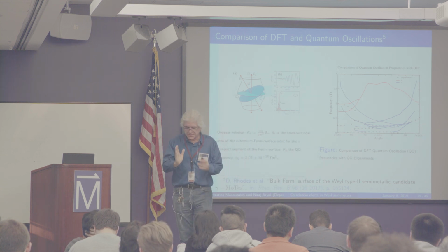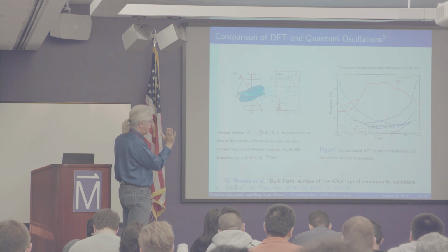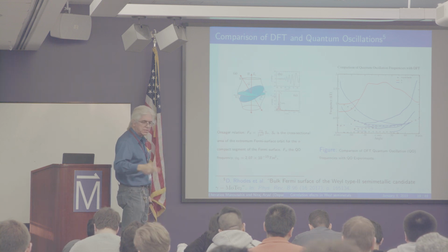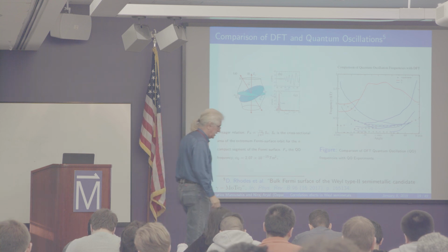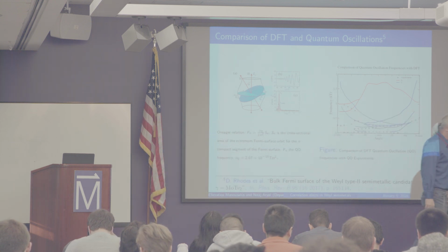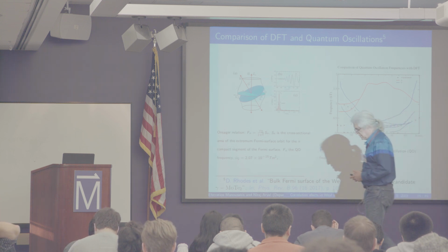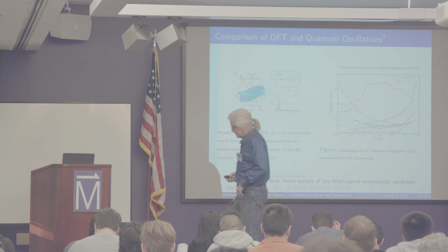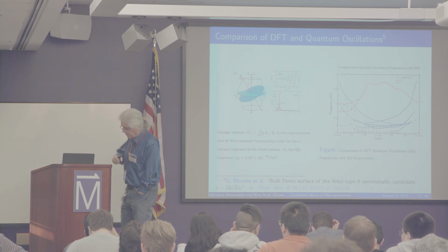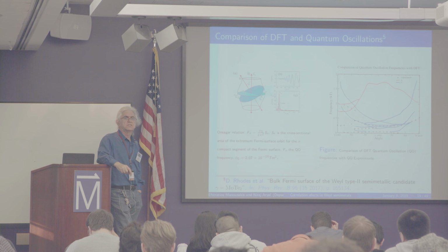They are just putting the sample, which is a crystalline sample, and they just change the angle of the magnetic field, and they are looking at the Shubnikov-de Haas oscillations. And from there, you get the frequency. Then the frequency is related to the cross-sectional area of the Fermi surface. So it's the angular dependence that exists as an experimental output, not the U dependence.